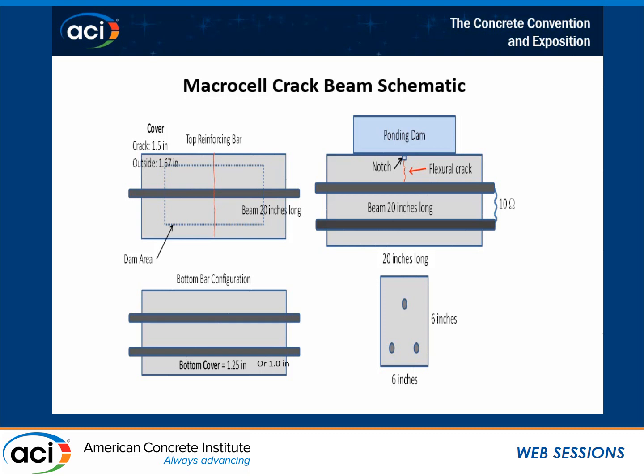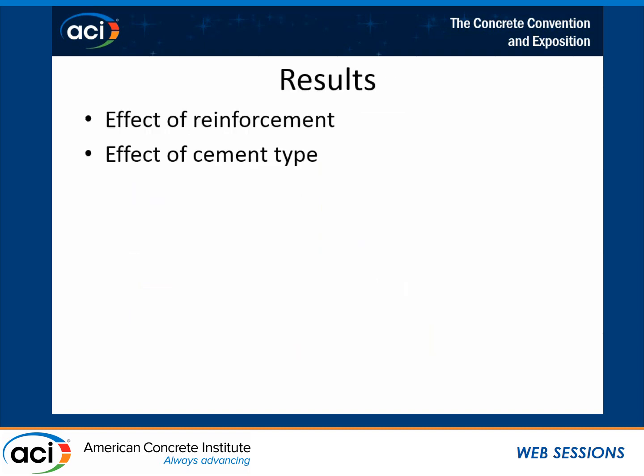and we had 1 bar on the top and 2 bars on the bottom, as we see here. Since they had a crack here, and this bar over here is very large, and most of the chloride's here, we had a 2 to 1 cathode to anode ratio, plus the bars on both sides of this are also providing cathodic current. So it's a very high cathode to anode ratio, which you would have in a real life structure. We have only a small amount of steel ever corroding at one time initially.